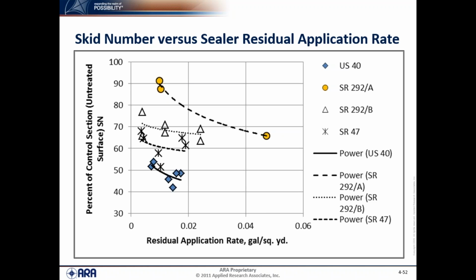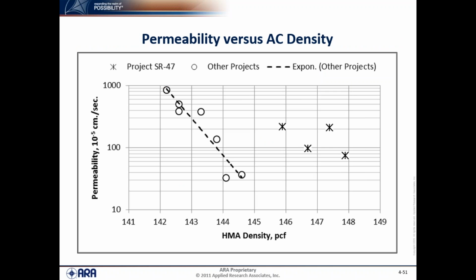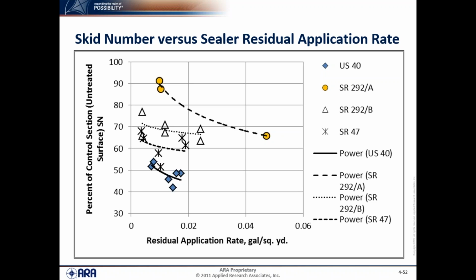This shows the skid values over time. Remember, that's only over about a 30-day period. The thing I wanted to show here is the average residual application rate, shown on the x-axis, and the y-axis is simply the percent of the control section. So we took the skid value for the control section and then looked at the skid value on the treated sections as a percent of that value. You can see there's a general relationship: the higher the residual application rate, the greater the decrease in the percent of the control section skid value. And that was generally seen on each project.